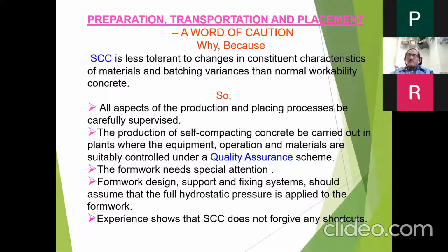So all aspects of production and placing must be carefully supervised. The production of self-compacting concrete is to be carried out in plants where the equipment, operation, and materials are suitably controlled under a quality assurance scheme. The formwork needs special attention. Formwork design, support, and fixing system should assume that full hydrostatic pressure is applied to the formwork, and not only full hydrostatic pressure, but as you know, the density of green concrete is approximately 2.4 to 2.5. So we have to say 2.5 times the hydrostatic pressure, that is, the pressure applied by water.